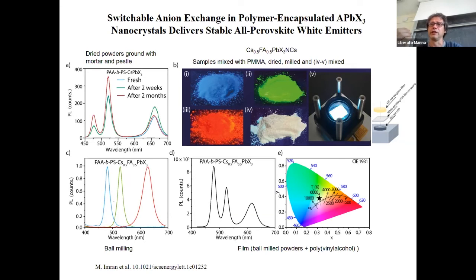Okay, now you have basically a film which is white emitting, and it's completely made of perovskite nanocrystals, and the excitation source can easily be just a UV lamp, as shown in this device architecture here. And by this you get again a white light emitting diode. So this is the color of emission of these three separate powders, and this is the color of emission from the resulting film that you see here.